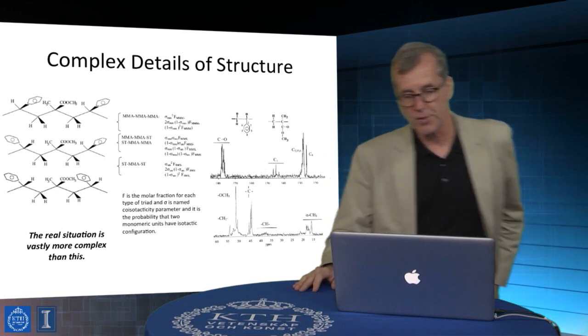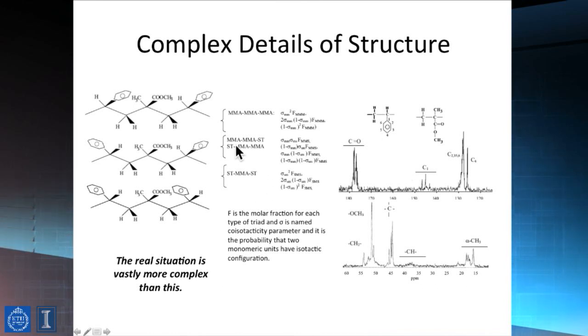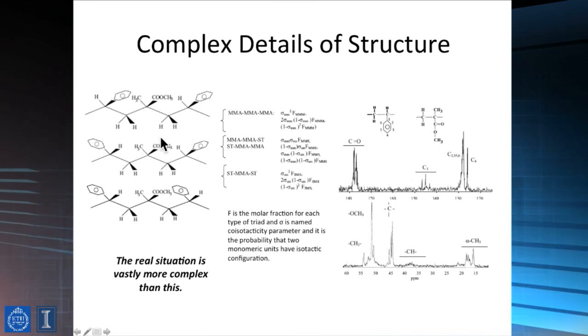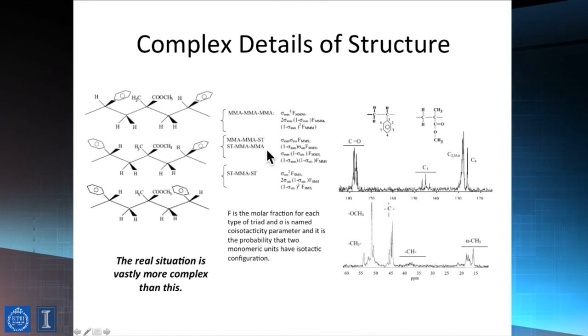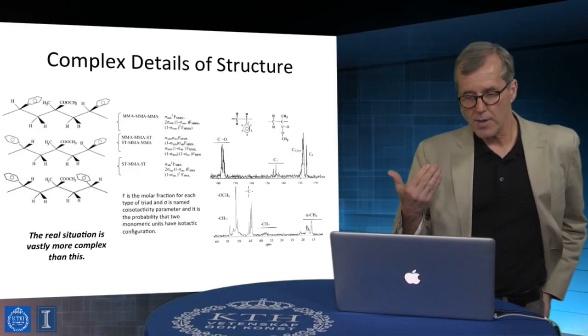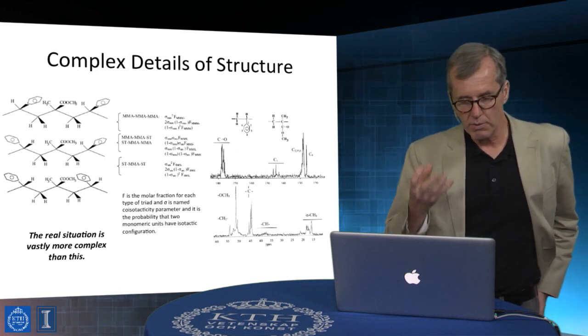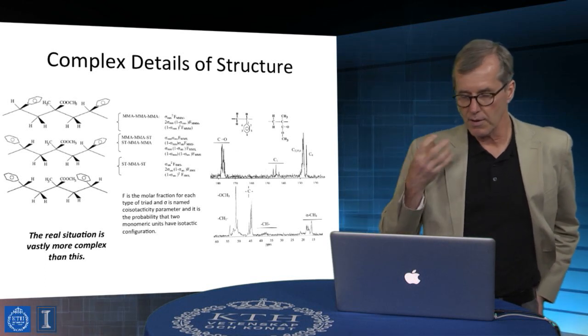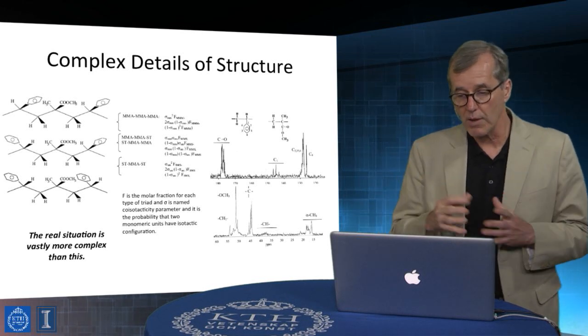How about complex details of structure? Well, NMR is, again, another powerful tool for doing that. So here are three-dimensional projections of different tacticities, or local tacticities, associated with a styrene PMMA copolymer. And you notice that we have different ways in which we can orient the methyl groups of the PMMA segment relative to sequences of the styrene-related component. This is something that I think would be really hard to get to in any other way that I can think of. And these are really subtle details of stereochemistry that are very local, but still relatively complex.